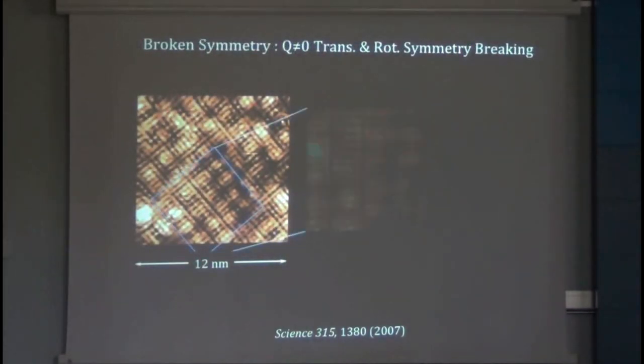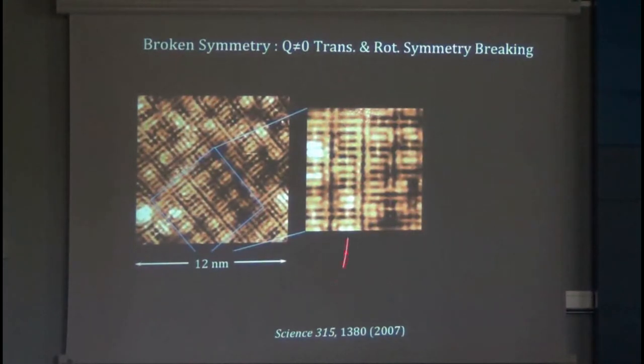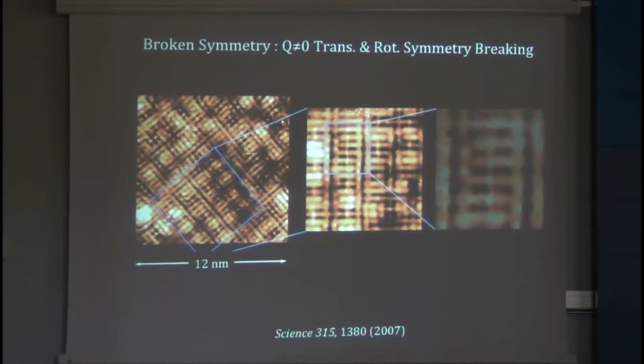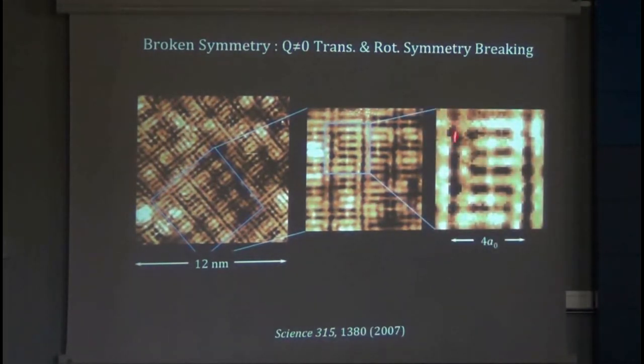Now we can examine those symmetries. If we zoom in a little bit, we find that they're unidirectional lines of charge, which are called stripes. And those stripes are bond-centered, so they're 4 unit cells wide, and they're centered on the oxygen atoms. So the symmetry line is on the oxygen atoms. So for the theorists, the fact that they're bond-centered stripes is very, very important.